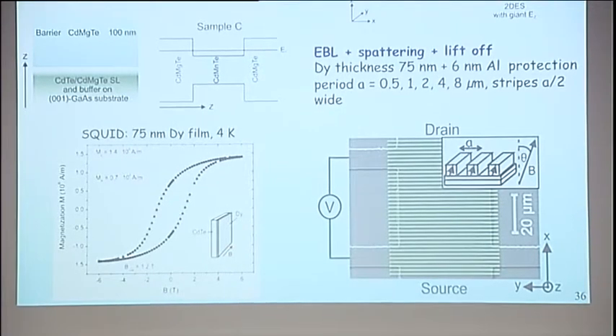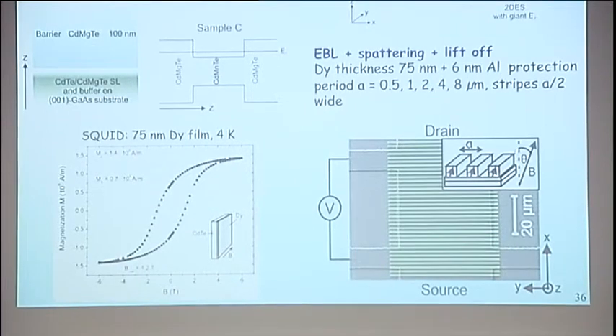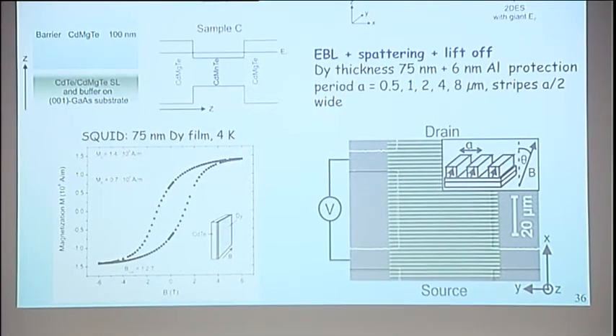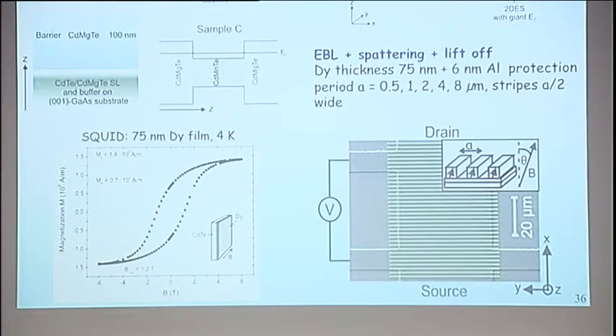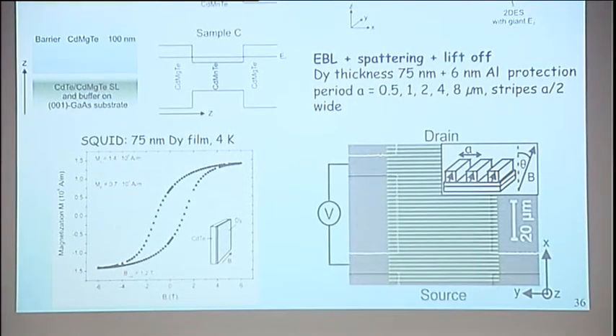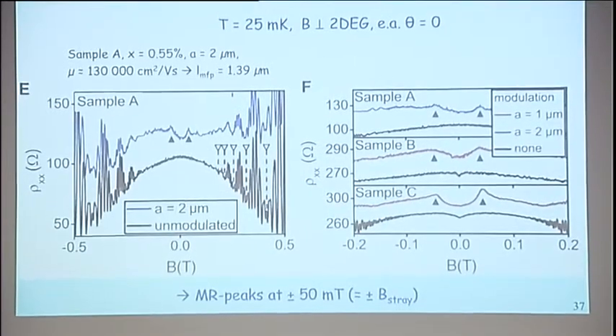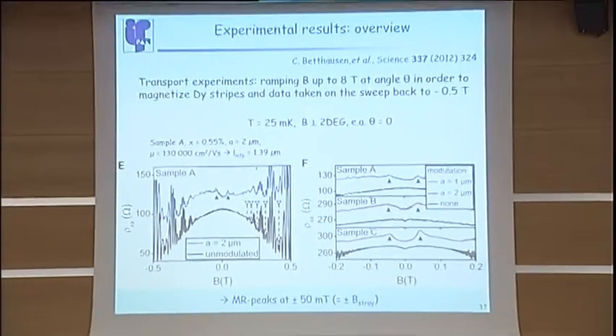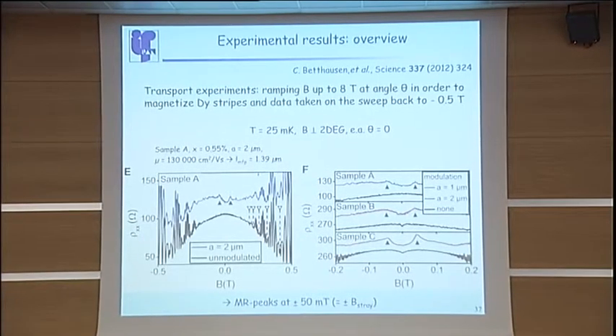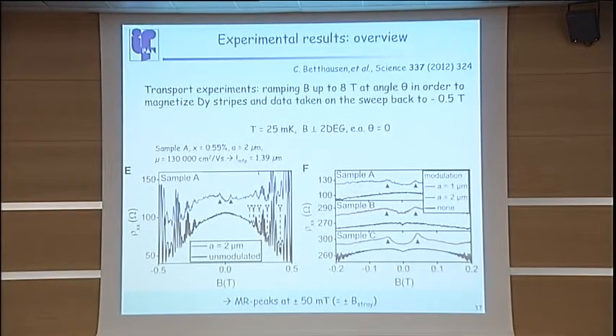So first you have to magnetize those stripes. You run at some angle to the normal, in a high magnetic field up to 8 Tesla. You magnetize and you collect data while going back from +½ up to -½. And what you observe, when you compare the two plots for unpatterned samples and samples with the pattern, is those two peaks, at roughly ±50 millitesla. This is not the effect of one sample. As you can see, this is observed in other samples as well, actually in all samples.